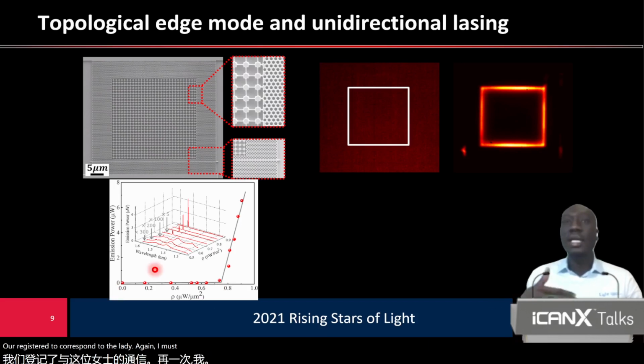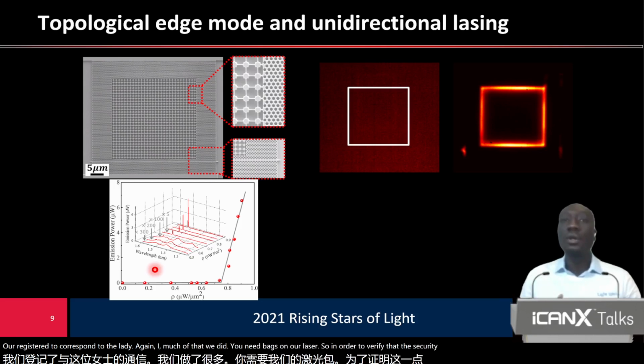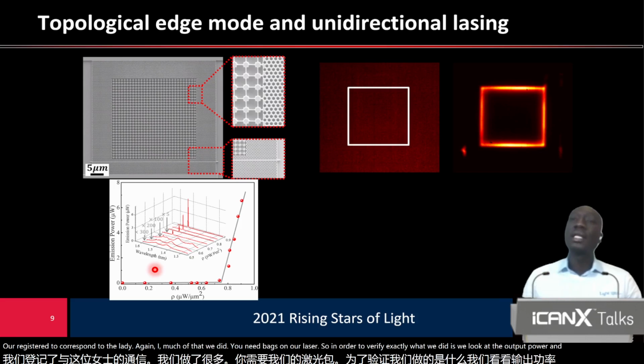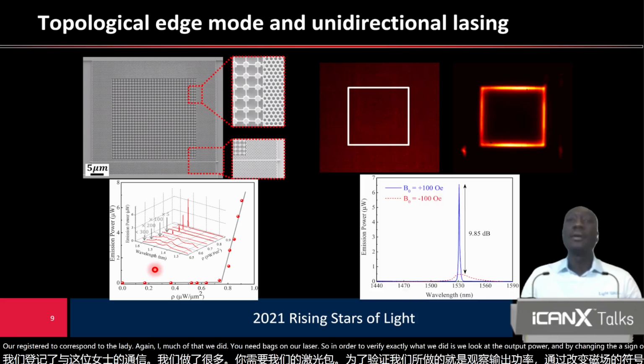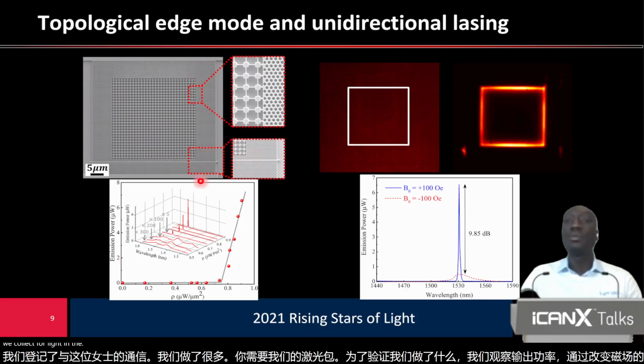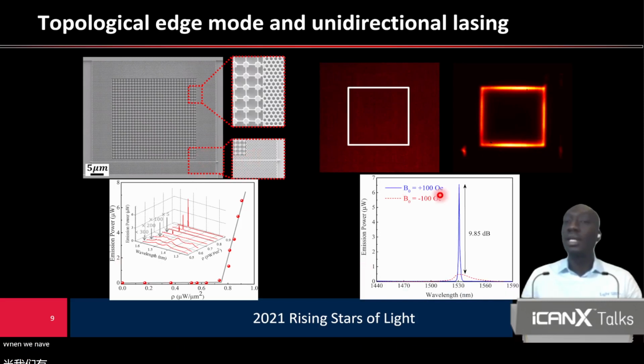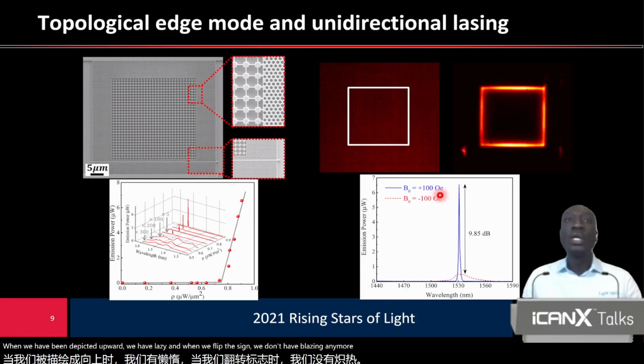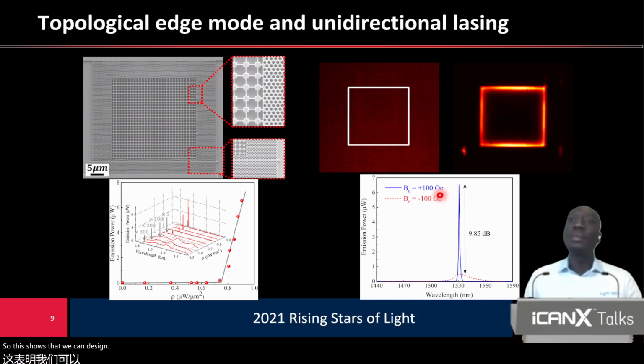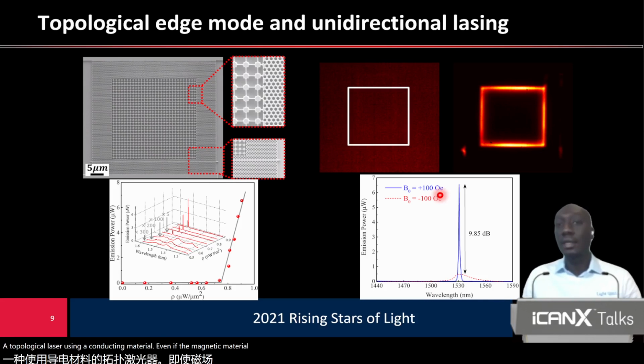Again, I mentioned that it is a unidirectional laser. In order to verify that, we looked at the output power and changed the sign of the magnetic field. What will happen? As seen here, when we collect the light at the output of the waveguide, when we have the magnetic field upward, we have lasing, and when we flip the sign, we don't have lasing anymore. So this shows that we can design, fabricate, and show for the first time a topological laser using magnetic material, even if the magnetic material is weak at that wavelength.